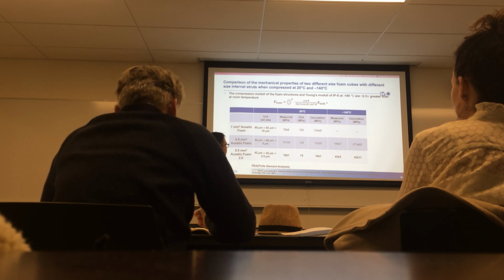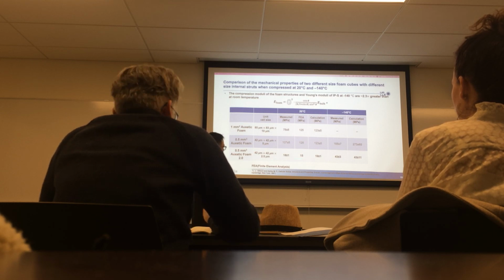And the calculation depends on this equation. This equation takes the unit cell structure and calculates the whole structure's elastic modulus. Depending on the unit cell thickness and length and the angle between the force and the edge, we can calculate the whole foam structure's elastic modulus. Comparing these results, you can see they match each other perfectly, especially for our second generation foam structures. And it proves that these results are convergent.